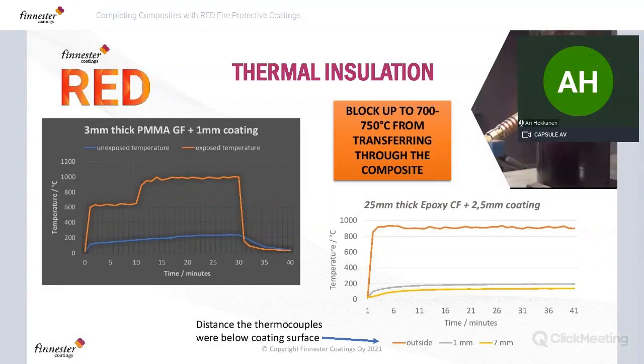And then just a couple of example slides of what sort of information we get out of our equipment. So this is the thermal insulation testing I mentioned a moment ago. And we think this is a pretty impressive result. We can keep temperatures on the unexposed face of a 3 millimeter thick thermoplastic glass fiber panel at around 200 centigrade, while the exterior is at 1000 centigrade for a 30-minute period. So this really shows, if you think back to the video that Ari showed earlier, that this thermal protection, this barrier protection is performing very well, and it's stabilizing. It keeps a flat profile on these temperatures. It reaches a steady state, and we are protecting a lot of the heat from getting through to the composite, and of course, therefore, protecting and preventing structural failure of the composite.